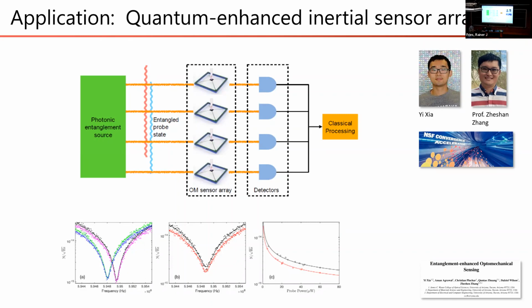If you do that, then you can make a measurement of the joint displacement with an imprecision below the shot noise level. So it's like making a squeezed light interferometric measurement of a single sensor, but instead of measuring the motion of one test mass, you're measuring the collective motion of several test masses. And this is interesting for inertial sensing because you're usually looking for not local forces, but a distributed force field.